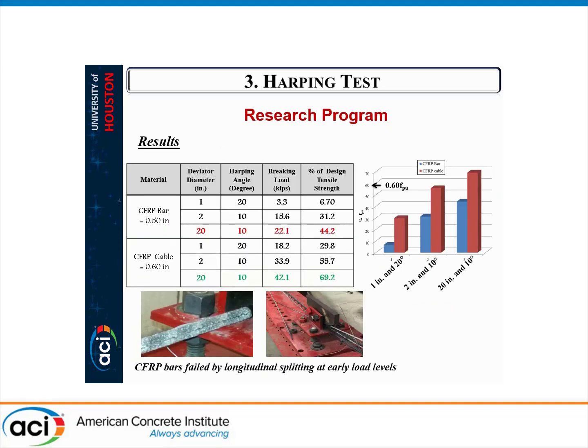The preliminary test results were not very satisfactory. First of all, 1 inch and 2 inch deviators in the case of CFRP bars retained a maximum of 31% of the design tensile capacity, and for CFRP cable it was higher, 55%, which is still not enough to be used. And also by increasing the deviator size to 20 inch, we still didn't get enough retention of tensile capacity, and one of the reasons is highly concentrated stresses at the location of the deviator, which caused premature failure of the CFRP.